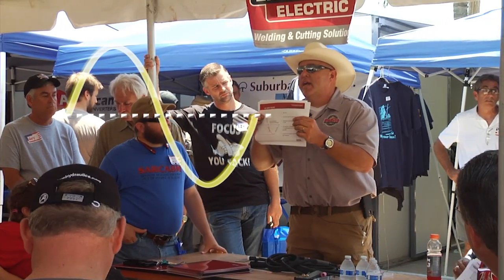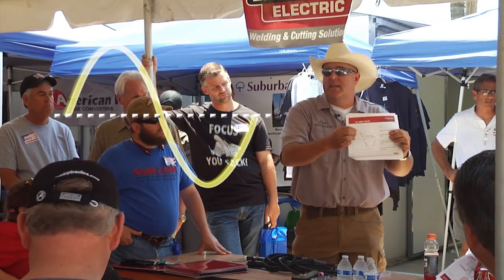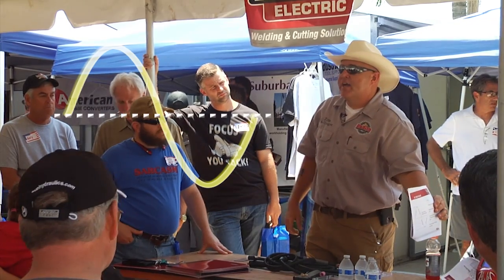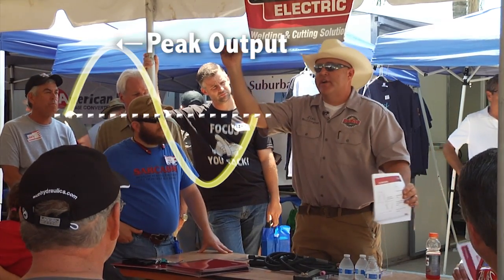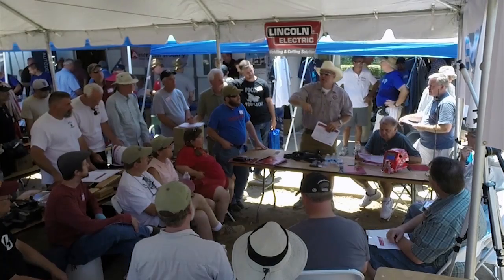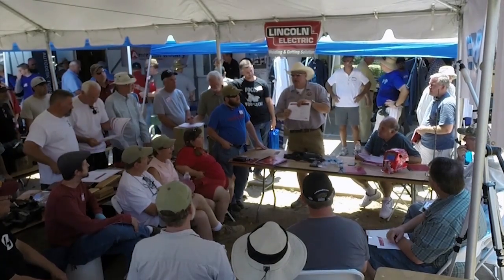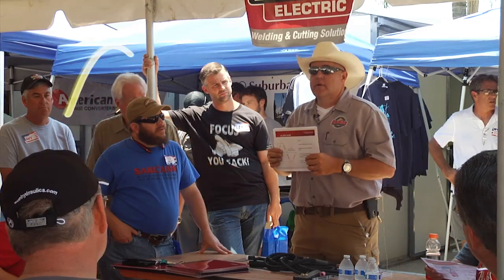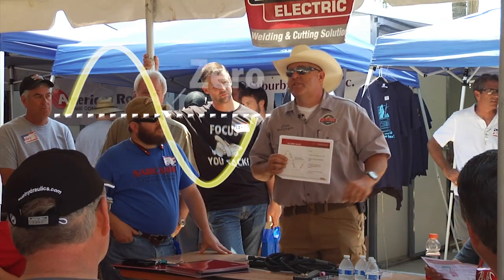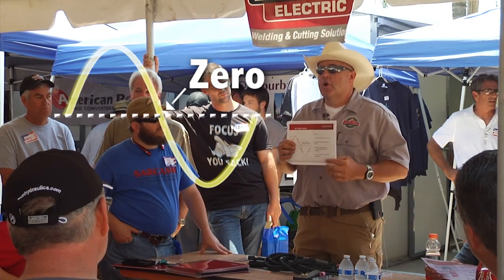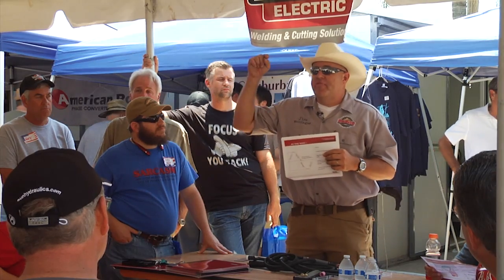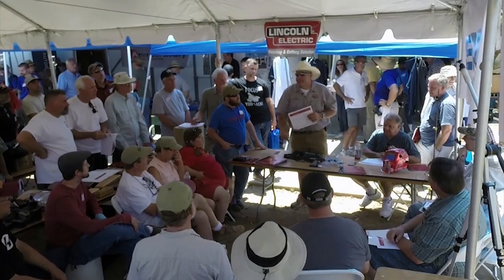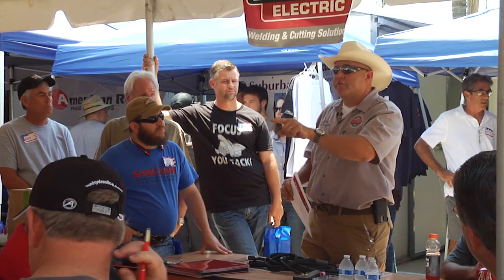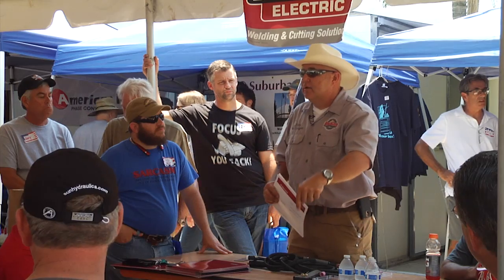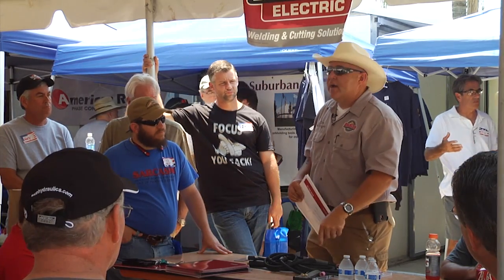What's interesting to point out here is notice that it's very, very lazy. See that sine wave? We're only at peak output for a very, very short amount of time. Then it begins to fall. When it gets to this line right here, guess what's happening? He is correct, nothing. We're at 0 volts, 0 current, 0 everything. But then we go to our electrode now negative. So where's all our heat? It's in the material. Remember, DC electrode negative, 70% of the heat's in the plate. We're doing all our work down here now.